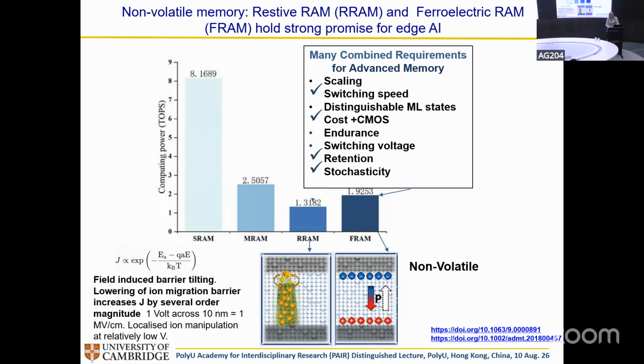And here, how would you move oxygen vacancies through a thin film at room temperature? They're not very mobile. They have a large activation barrier. Well, that happens by reducing the activation barrier. So the current is proportional to the activation barrier minus the field that you apply. If you have a large field across your film, then you can reduce that barrier. And as you see here, 1 volt across a 10 nanometer film is around 1 megavolt per centimeter. It's quite a large field, and the films are all around that thickness. So you have this field-induced barrier tilting, and you can lower that migration barrier and cause these ions to move with the voltage. So that's the two basic simplistic technologies, but the materials are challenging.